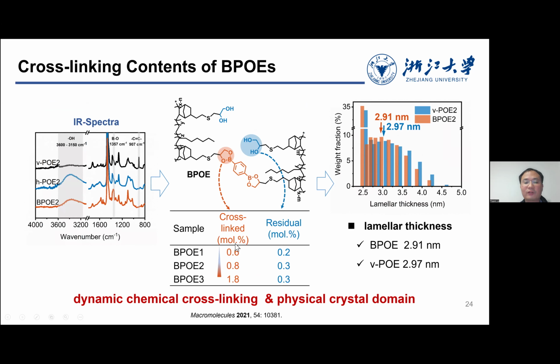We can increase from 0.6 to 1.8% more, and the residual one, we still have some residual diol that does not react. The percent is about 0.2 to 0.3. And we also characterize the lamellar thickness and crystallization structure of these polymers. You can see after introducing the cross-linked structure, their lamellar thickness becomes a little bit smaller, from 2.97 nanometer to 2.91, just a little bit of change, not too much.